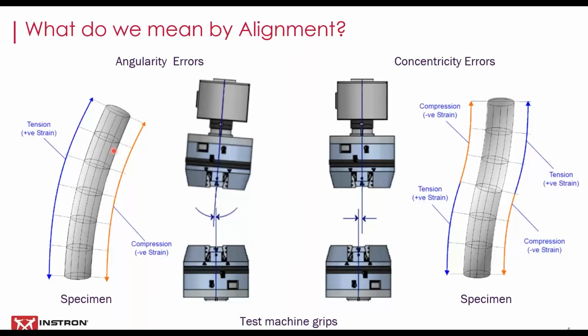And of course, these strains would be summed with the overall axial strain. But they're going to result in a non-uniform strain distribution across the specimen. In the other case, the grips might be parallel. I mean, these are extreme cases, but they might be parallel, but they might be offset. So we've got a concentricity error here. And you can see again, this would create some kind of S-type bending in the specimen, which is probably worse than the gradual bending because the curvature is larger for a given size of specimen.